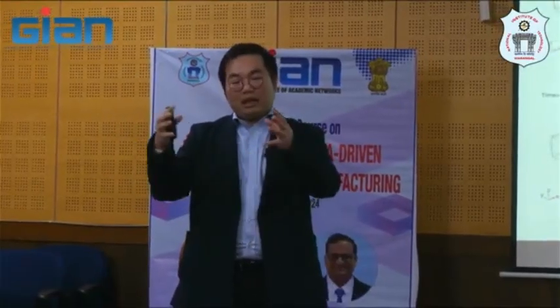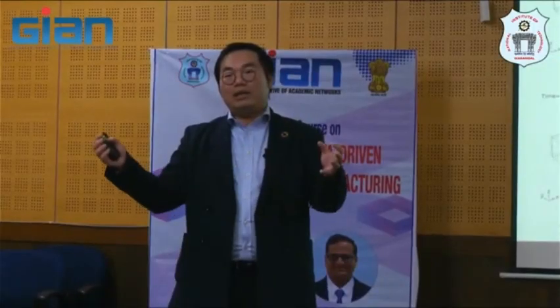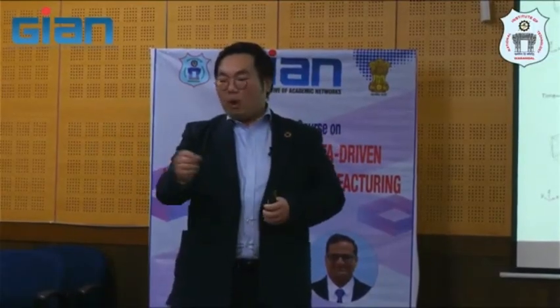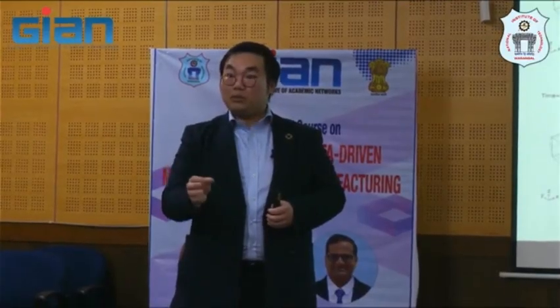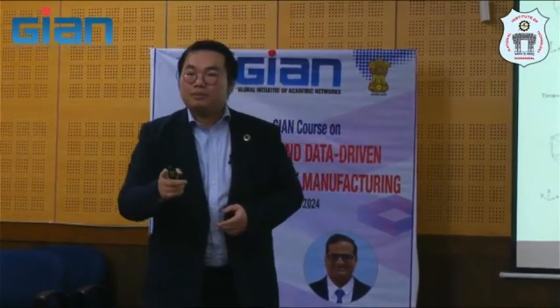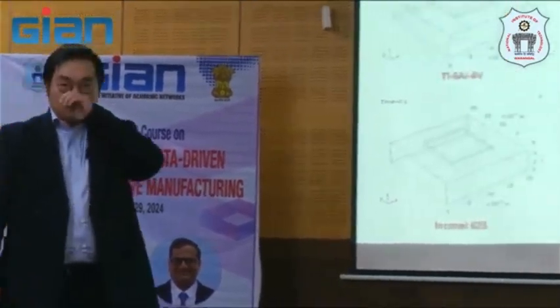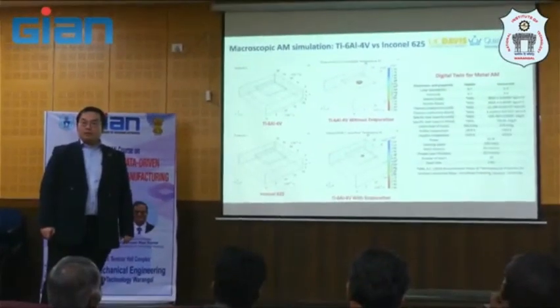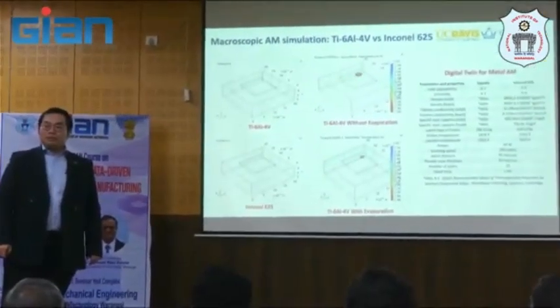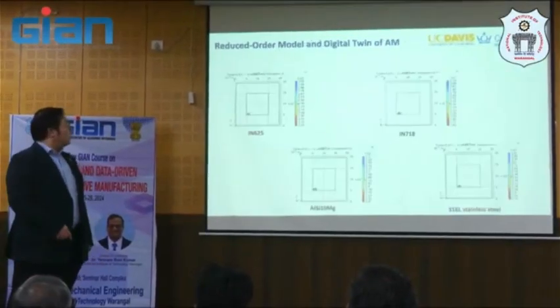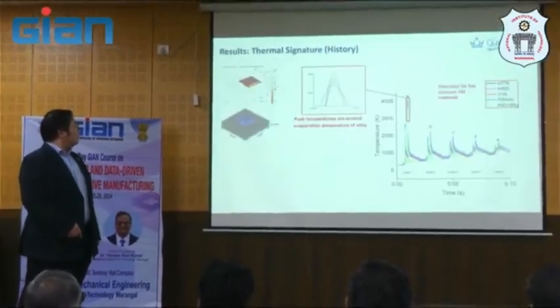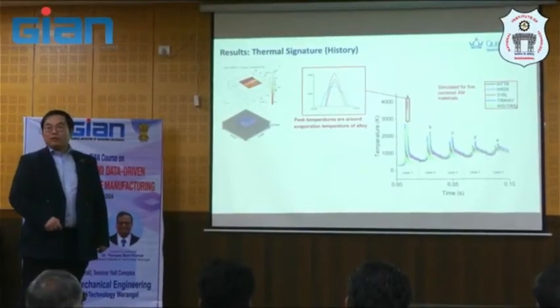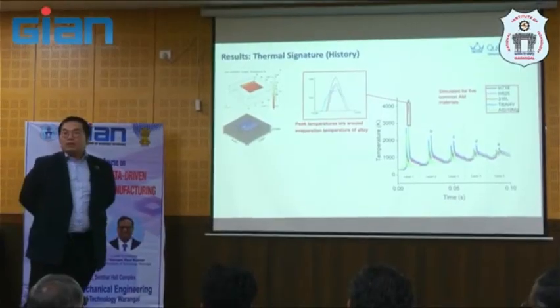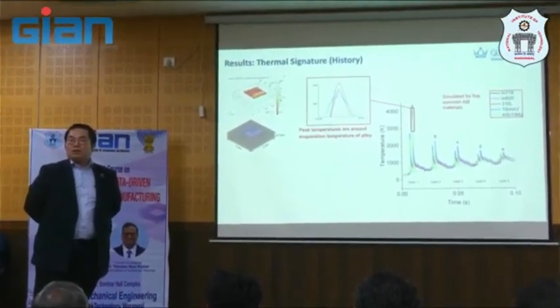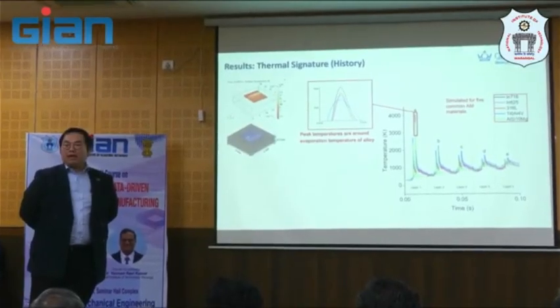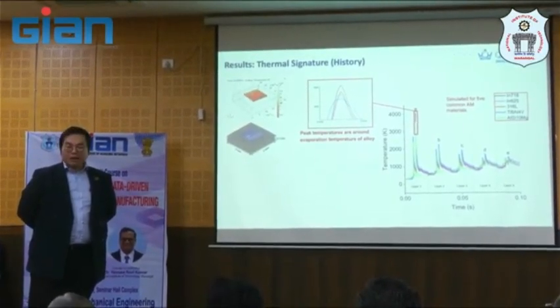That's why the heat contained in the material is actually lower, and that means once the energy here is lower, the size of the melt pool is smaller. Your question is? Sir, in the legends that we are seeing over here, the peak temperature is somewhere around 3200 Kelvin, both these legends, with and without evaporation. Without, it's about 3,000 Kelvin, which is around the boiling temperature. I'm just asking whether the peak temperature will also reduce when we consider the effect of evaporation. Yes, if we consider evaporation, peak temperature will be reduced.